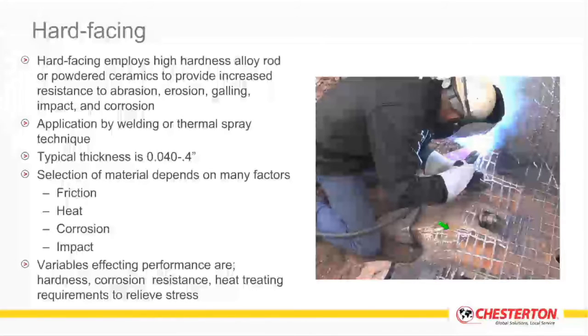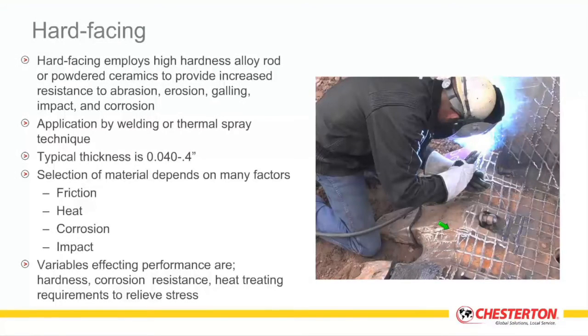Now, when you're getting to the point of choosing materials, there are various technologies that have been used in the industries for many years. One of the most common is hard facing, and this can employ a welding process using an alloy rod, or it can employ what's known as a thermal spray approach, applying powdered ceramic, powdered metal, or metal rod into a high velocity gas flow, which will liquefy the material and then impinge it onto the surface at high velocity. If it's hard face welding, it's simply laying down rod on top of the surface in multiple passes. Typical thickness of these materials can be anywhere from 40 thousandths of an inch and up. They can be applied as thick as maybe up to 3/8 of an inch.